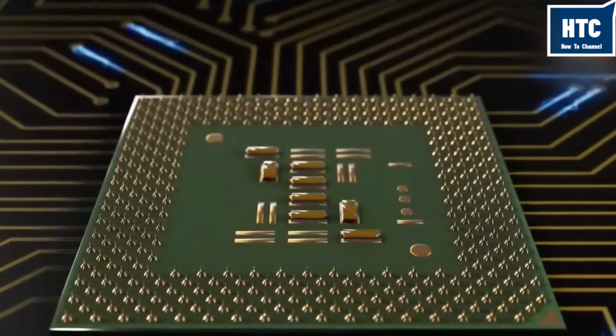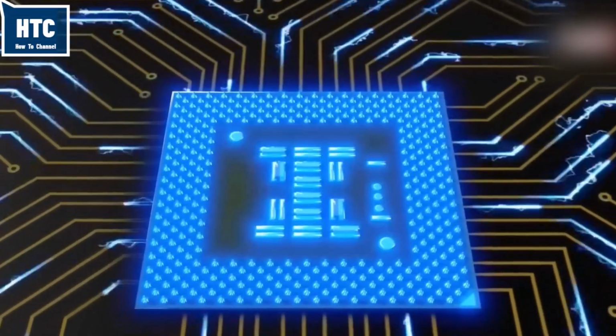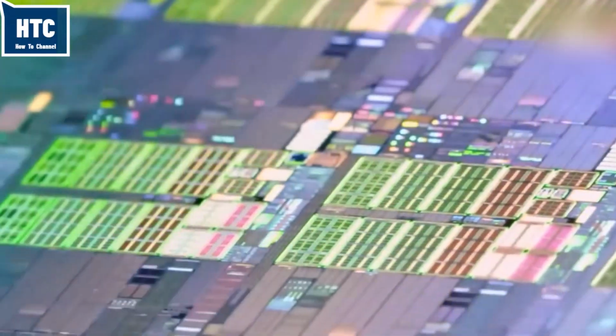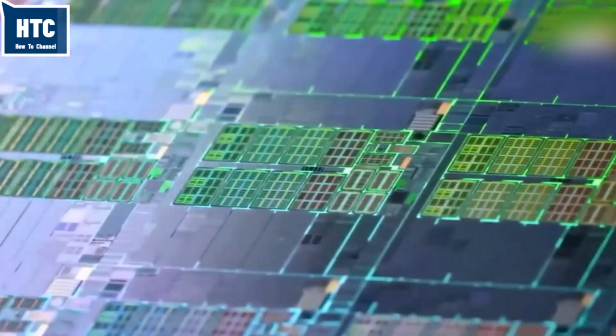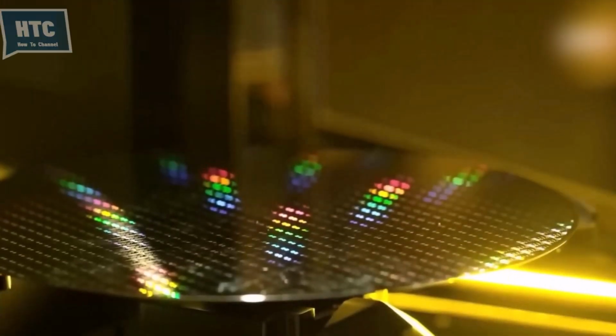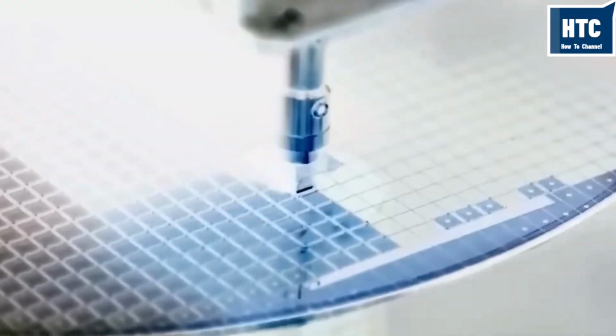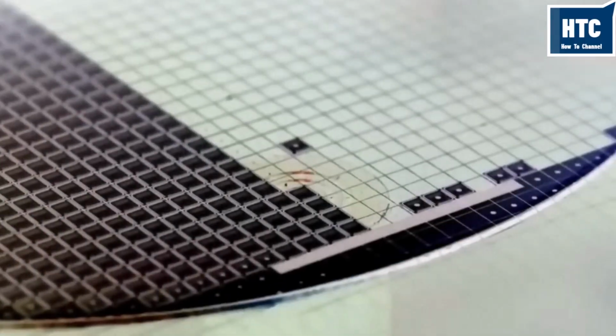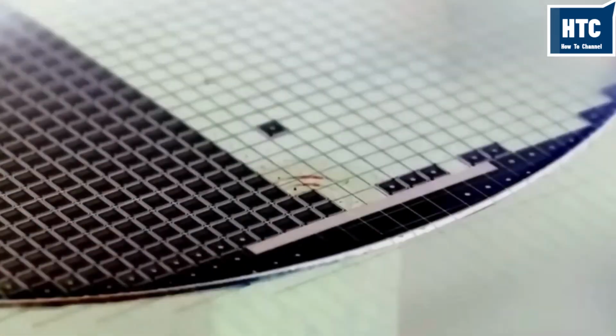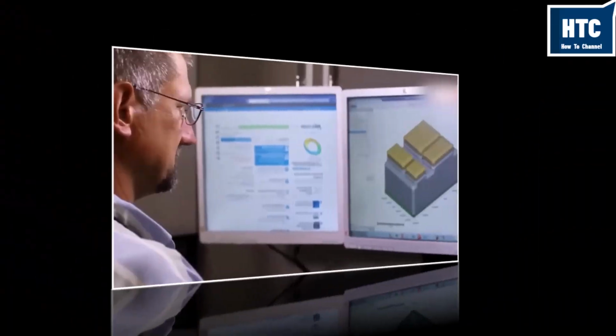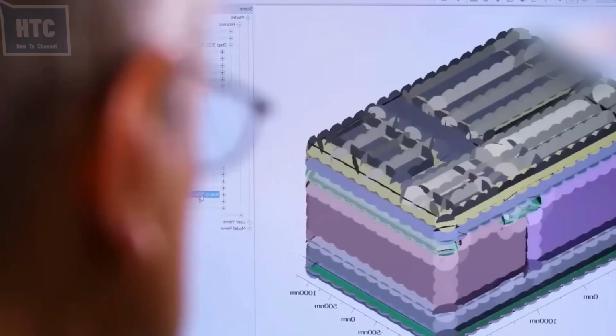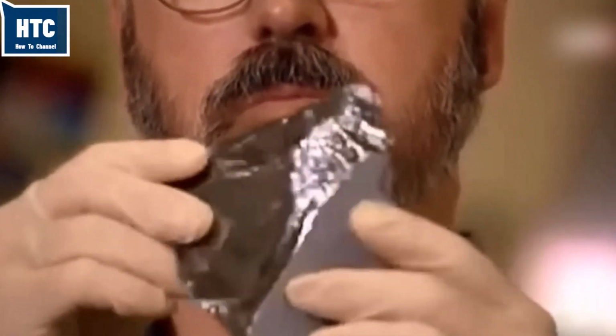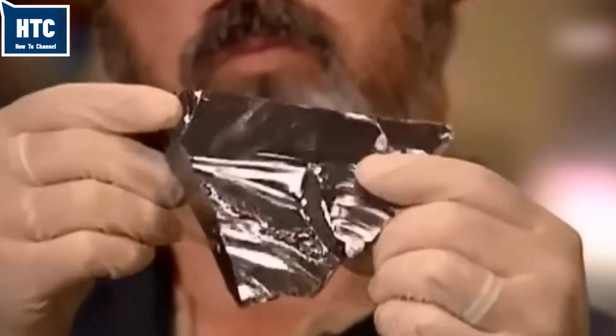But 98% purity is nowhere near enough for electronics. We need the 9 nines, 99.9999999% purity. To achieve this, the silicon is crushed and reacted with hydrochloric acid to form a gas called trichlorosilane. This gas is distilled and purified, then decomposed back into solid silicon rods using the Siemens process. This is now electronic-grade silicon.